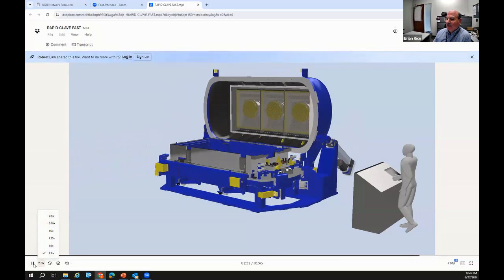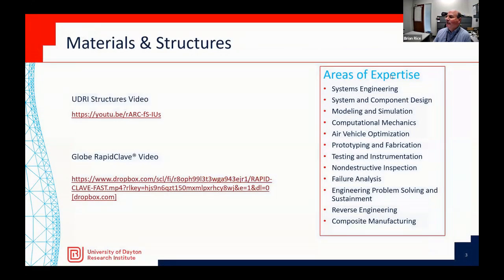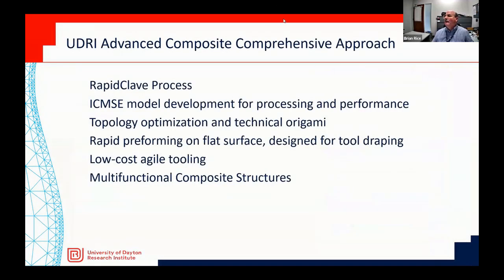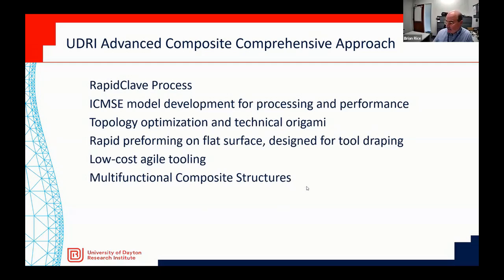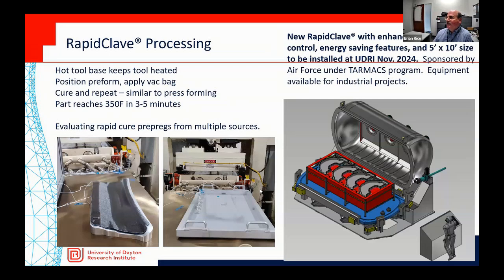So presently we're working with at least 4 major prepreg manufacturers that have high rate cure prepregs, primarily for aerospace, and running those in the current rapid clave and making demo parts and so forth. So let me share back to my PowerPoint slide. So I'll do a little deeper discussion on some of the things I just showed you. So again, here's the rapid clave. We have what we call rapid clave number 1, which is what we're using to process different prepreg materials and different tooling concepts today. Generally, you're looking at roughly a 30-minute cycle time based on the kinetics requirements of the materials that are out there for aerospace.